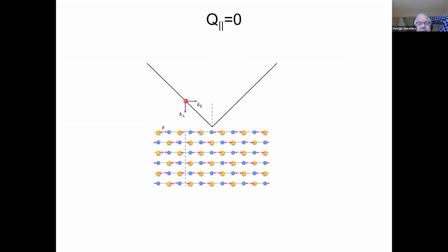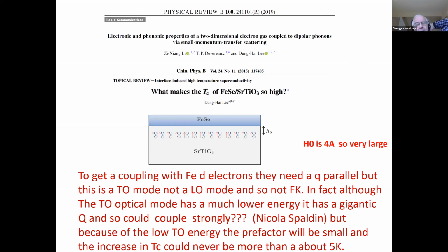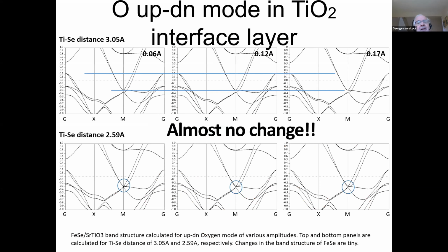However, in TC, that phonon frequency is the prefactor. And so I can't imagine that it could give you anything more than perhaps a 5 degree Kelvin change. We actually did what I call a poor man's electron phonon coupling calculation, just to see what happens if we move the oxygen atoms in this polar mode in the strontium titanate and look at what happens to the iron selenide band structure. And remember, the iron is about 4 angstroms away from the surface of STO.